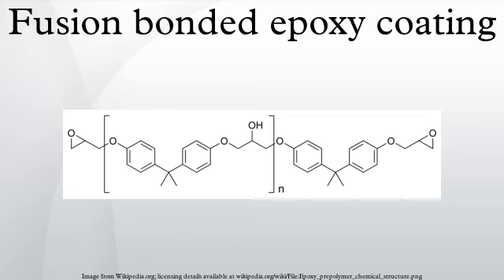Various types of curing agents used in FBE manufacture include dicyandiamide, aromatic amines, aliphatic diamines, etc. The selected curing agent determines the nature of the final FBE product: its cross-linking density, chemical resistance, brittleness, flexibility etc. The ratio of epoxy resins and curing agents in a formulation is determined by their relative equivalent weights. In addition to these two major components, FBE coatings include fillers, pigments, extenders and various additives, to provide desired properties. These components control characteristics such as permeability, hardness, color, thickness, gouge resistance etc.